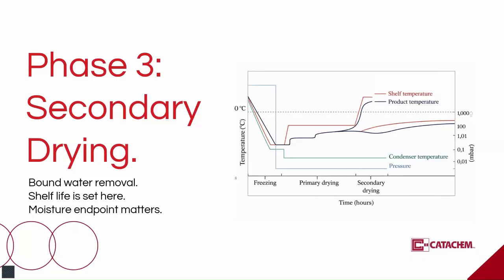In secondary drying, you typically increase shelf temperature under continued vacuum to drive desorption. But you must remain below thermal limits for the active ingredient, the excipients, and the container and closure system. Overheating can denature proteins. Under drying can leave residual moisture that is too high, leading to stability failures months later. At Catachem, we treat secondary drying as an engineered endpoint. We define a moisture target range tied to performance and stability, and we confirm it with quantitative methods, typically Karl Fischer titration. We do not rely on time alone as proof of dryness.